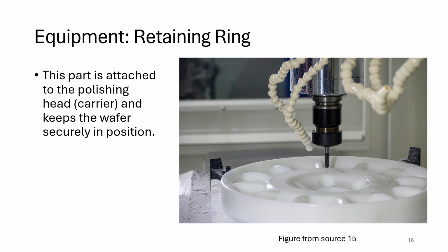PEEK is a material that is typically chosen for this application because of its dimensional stability, chemical resistance, low outgassing levels, and its excellent abrasion resistance. Typical PEEK retaining rings last for approximately 12 pad changes.